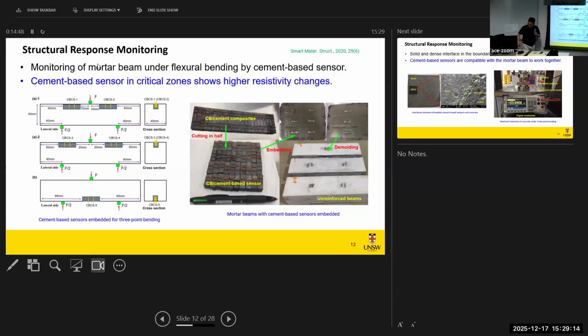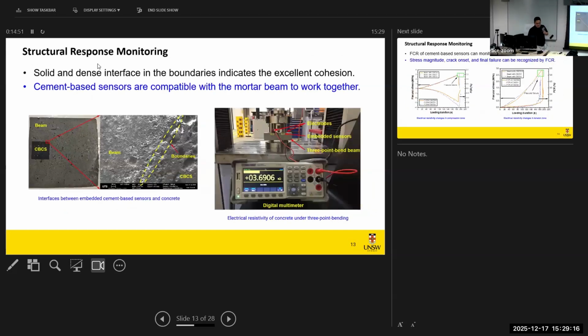Before the test, let's look at the interface between the cement-based sensors and the mortar beam. We found that the boundary between them is very solid and dense. So this implies the cement-based sensors and the mortar beam are compatible with each other and can work together very well. And this one shows the bending test conducted in the laboratory.